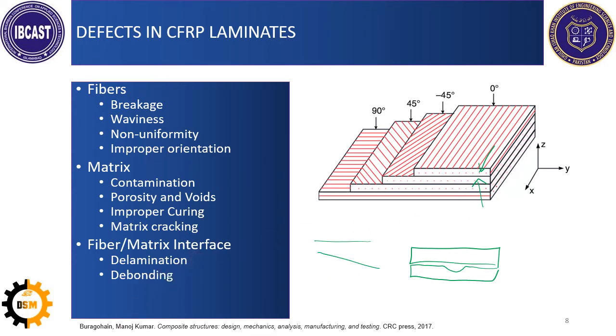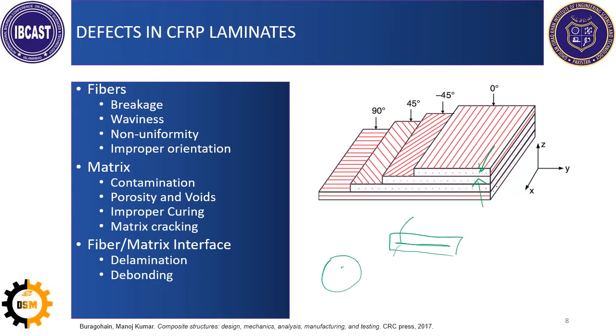Another defect can be debonding. Debonding means that if you have the reinforcement and then you have the resin inside, and this reinforcement is disconnected from the resin, so the interaction of the reinforcement with the resin is weakened and it is debonded. So there is no connection between the fiber and the resin. This will result in decreased properties of the composite, and it is a failure.